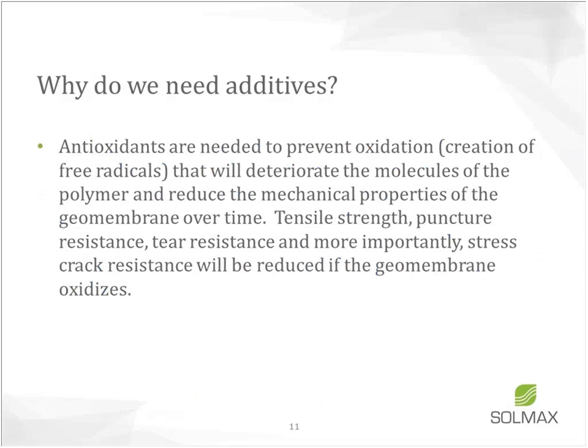Antioxidants are needed to prevent oxidation and creation of free radicals that will deteriorate the polymer's molecular structure and reduce mechanical properties — tensile strength, puncture resistance, tear resistance — and most importantly, stress crack resistance. When a geomembrane at the bottom of a landfill has lost all its antioxidants and starts creating free radicals in 500 years, it's probably not going to tear from an applied force; it's more likely going to crack. So stress crack resistance is very important to evaluate.